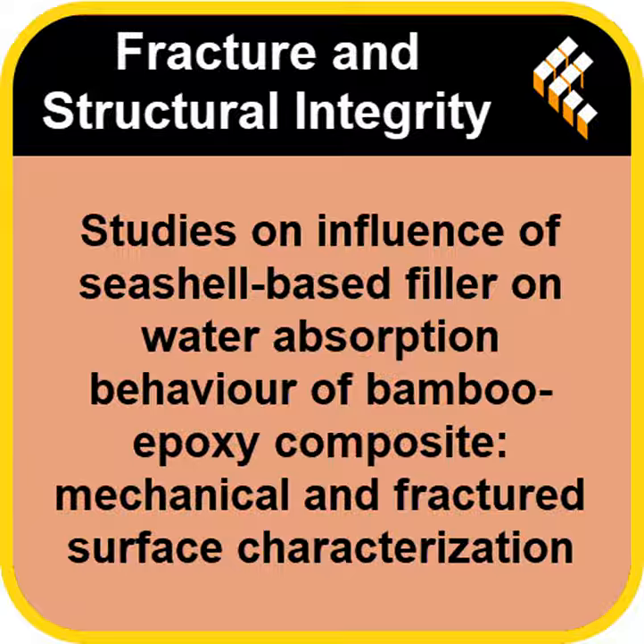30%. That's a huge improvement. But hang on, you said it wasn't just more is better. What happened at 9% filler? Right. This is really important. At 9% loading, the water absorption actually went up slightly to 4.95%. Still better than the control, but worse than 6%.